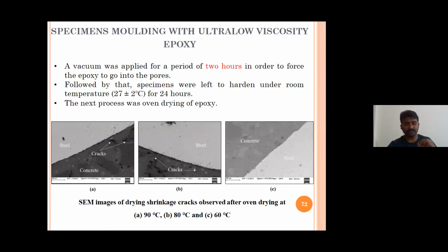Then again, as I told you, this is another parameter which we should look into while going for resin observation. It is molding the specimen with ultra low viscosity epoxy and drying it. As you can see, I wanted these patches to look very dark in BSE images. So that's why I have to incorporate the ultra low viscosity epoxy, wherein it appears dark in BSE images. Once I apply it, I have to dry that epoxy before I grind it, because of drying shrinkage. It's like a paste.